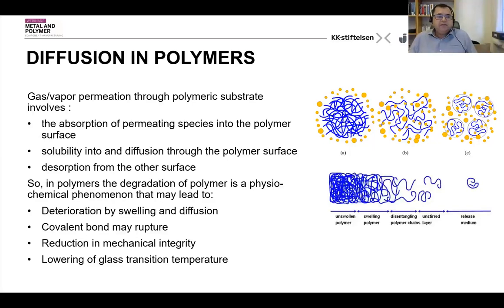So in polymers, the degradation of polymers is a physiochemical phenomenon that may lead to deterioration by swelling and diffusion. The covalent bonds may rupture during this process. It may lead to reduction in mechanical integrity of the polymers. And the worst effect is the lowering of the glass transition temperature of the polymers.